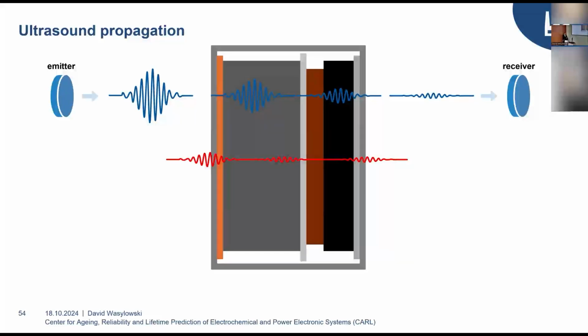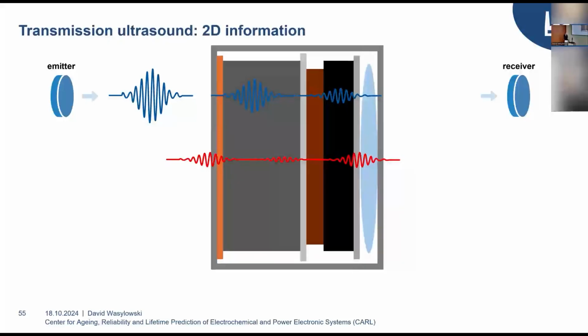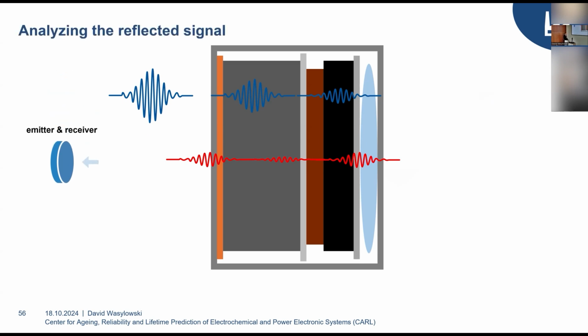So if we revisit this two-dimensional simplified battery cell with this deposit in the middle, and we get all of these reflections and transmissions we discussed earlier, and we now introduce a gas accumulation on the rear end of this battery, we will get a complete reflection of the sound wave, which makes this deposit not measurable for the receiving transducer on the other side. But the information is still being generated here because we are still getting a reflection. So if we would now just analyze the reflected part instead of the transmitted part, we would in fact be able to measure the reflection at this deposit.